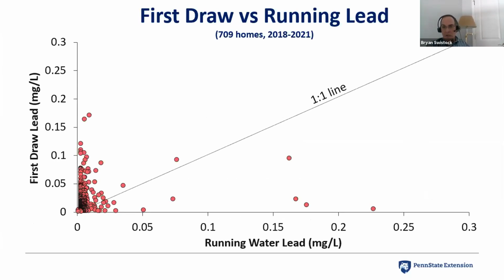Now, if we look at the private water system data that we have, this is looking at first draw lead versus running water lead. And anything above that 1-to-1 line would indicate that we've reduced the lead down. Anything below it would indicate that the lead actually went up in the running water sample. And so what we see are a lot of samples down here where they have fairly high first draw lead concentrations, but very low running water lead concentrations. So that's kind of what we would expect in a corrosion situation where we're drastically reducing that concentration by running the water.